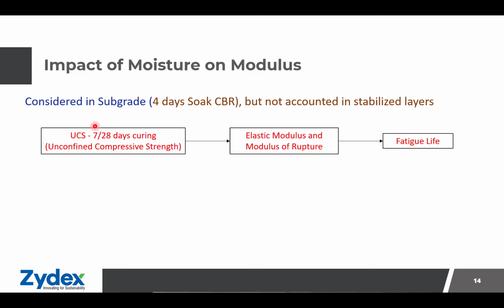Further, we also need to consider the impact of moisture on modulus. For the subgrade, we consider the 4-day soaked CBR. This is considered in order to simulate the worst case scenario that can happen in the field. But for the stabilized layer, are we really considering any correction for the modulus, or are we measuring the modulus under wet condition? That is questionable.